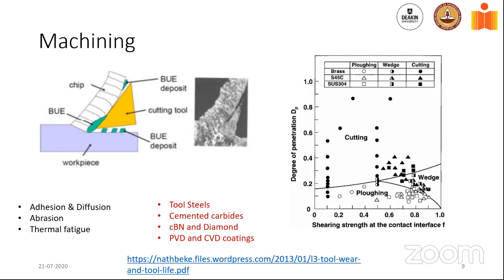One more example of wear, but a good example of wear. Without wear, you cannot have machined surfaces. All the machine shops would go dead if you didn't have wear taking place. And it's a very complicated phenomenon. You have a cutting tool that gets in contact with the workpiece. It digs into the workpiece, causing intense plastic deformation and shear. And as the intense plastic deformation takes place in a very localized region, the heat builds up and the surfaces oxidize and slide against the cutting tool, leading to what we call crater wear.